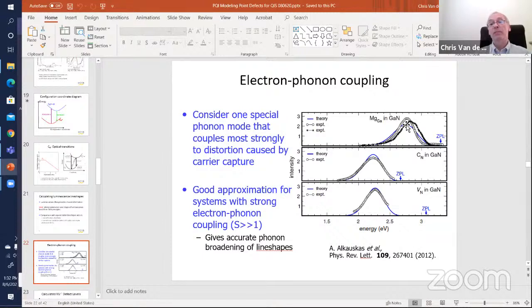That can be done, for instance, by specific implantation procedures. I didn't talk about it, but the NV center in diamond is typically created by having a nitrogen-doped material. So the nitrogen atoms are already there, and then doing irradiation or implantation creates damage, which creates the vacancies, and some of those vacancies will be next to a nitrogen atom. Now, you can do the implantation with almost nanometer size control by using very narrow beams or templates, masks. So that can be done with very high precision.